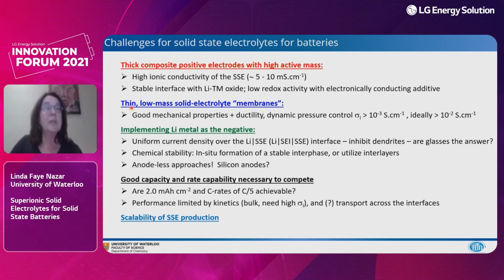As for the separator, we need to find thin, low-mass membrane type materials that have good mechanical properties, ductility, good dynamic pressure control, and ideally have conductivities as high as 10 to the minus 2 Siemens per centimeter. And implementing lithium metal is kind of the holy grail in these systems. It means we have to achieve uniform current density over that interface and inhibit dendrites.